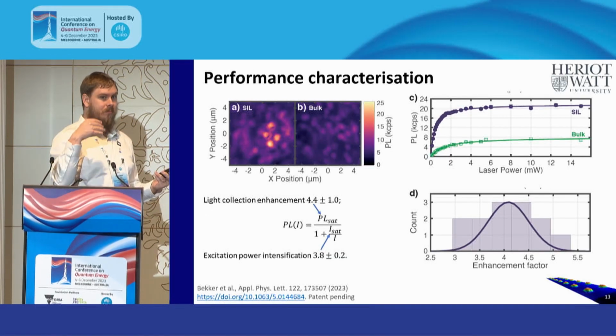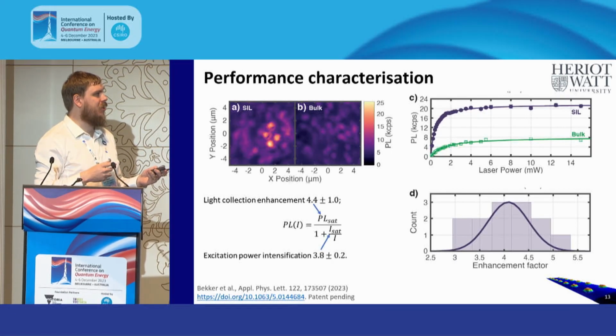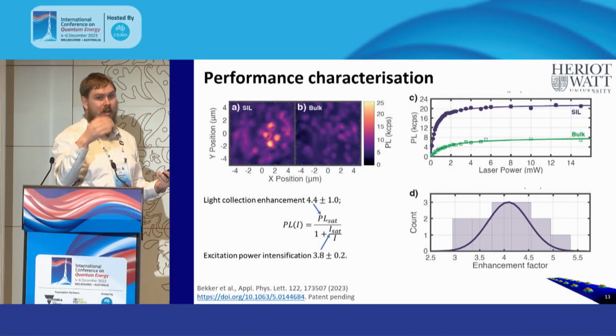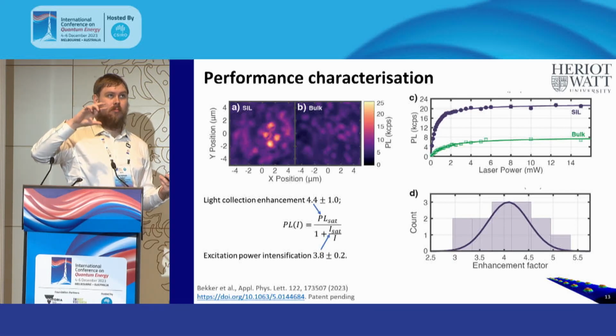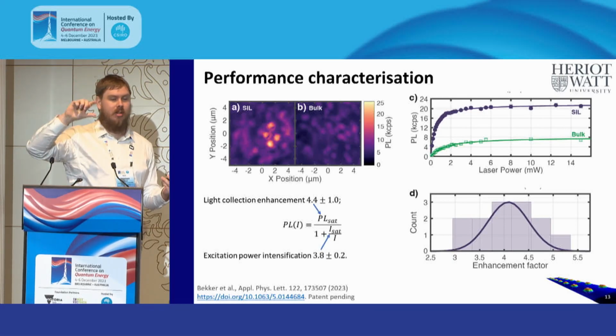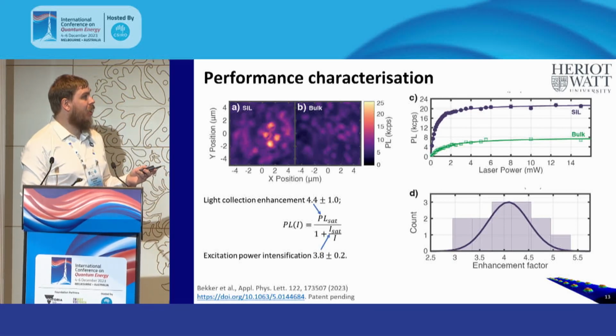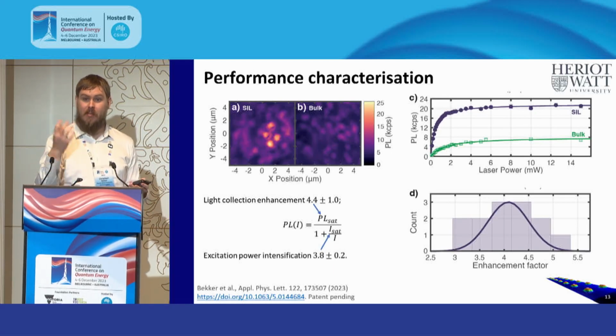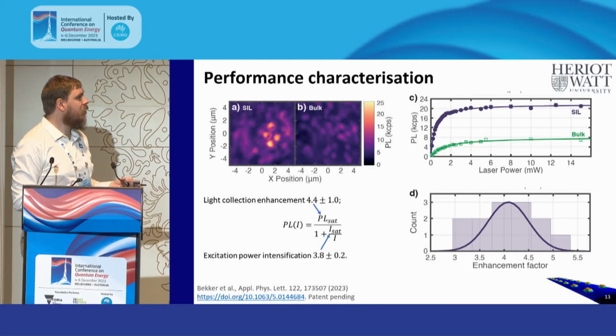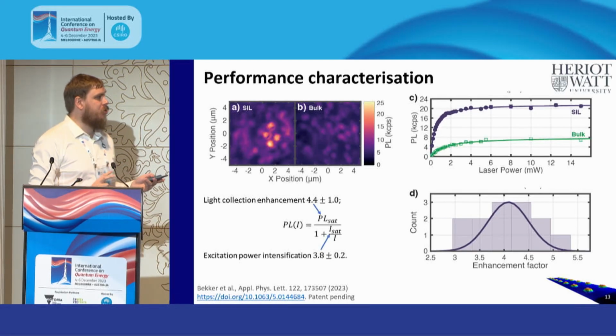Just as you pump your emitter, it has this saturating behavior, as it's only able to absorb and emit light at a certain rate. And here you can see that the amount of light we collect from an emitter inside a lens is enhanced. There are two elements that I should mention here.